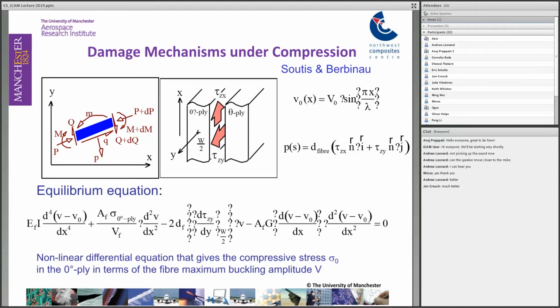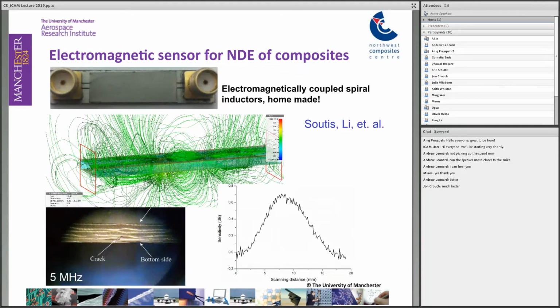And the effort now is focusing on how we can identify those critical damage modes that take place inside the component non-destructively. And here we can see an electromagnetic sensor, which is an electromagnetically coupled spiral inductor. It's a very low-cost, homemade sensor that we developed here at the University of Manchester, and it enables us to identify non-destructively delaminations that can happen not only in UD pre-preg laminates, but also in woven fabrics. But much more work is required.